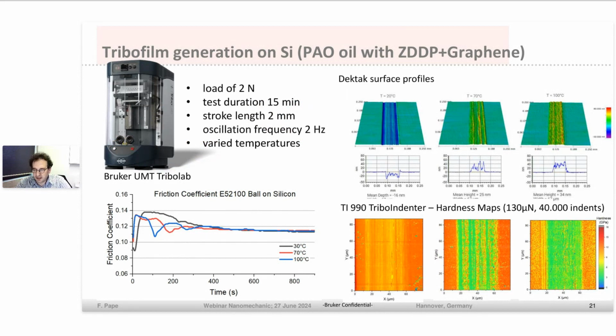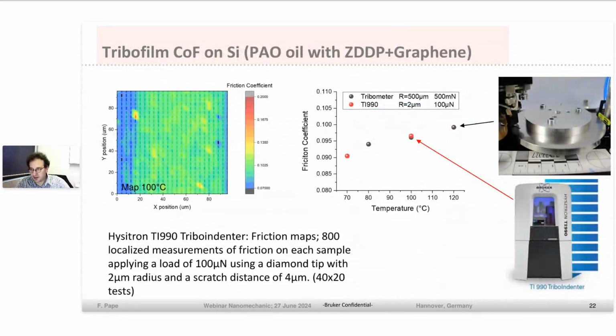And Uda did some very nice measurements of the hardness on these layers, showing us the hardness on the specific tribofilm itself with values of 3 to 4 gigapascal. And what is quite new, he did an array of nano scratch tests on this kind of tribofilm, shown here on the left, for the sample formed at 100 degrees Celsius in the tribometer. And we can see that we have here a local coefficient of friction of slightly below 0.1.